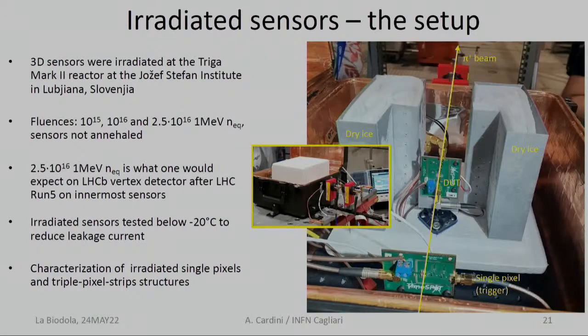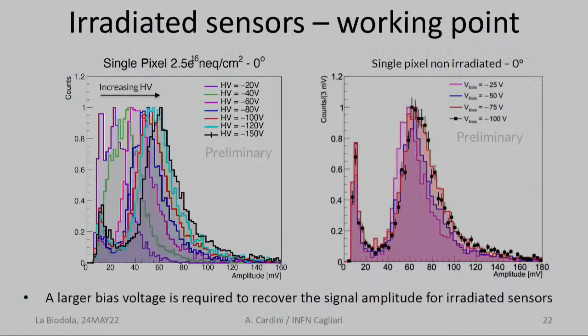Let me come to the final part of this presentation: the very recent results on irradiated sensors. We irradiated the sensor at the reactor in Ljubljana up to 2.5 times 10 to the 16, 1 MeV neutron equivalent. This is what one would expect on HL-LHC Vertex detectors in a future upgrade after Run 5, on the innermost sensor. The setup is the same one, but we are using dry ice to operate those detectors with a reasonable leakage current, and we characterize single pixel, triple pixel to measure the efficiency, and so on.